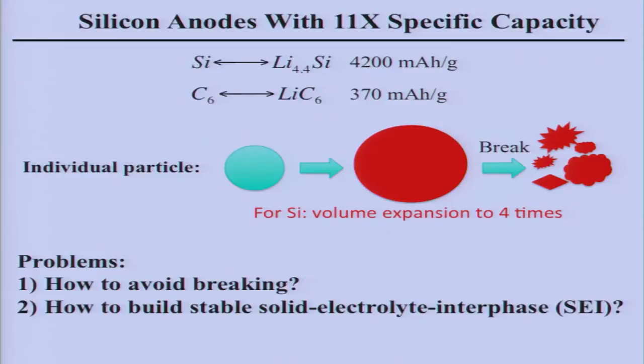So silicon has been my home run since the beginning. This is an example of a silicon crystal structure that can store 1 silicon atom for 4.4 lithium. You calculate that, and this is the capacity you gain. It's 11 times that of graphite carbon. But the problem you're facing is that silicon volume expands to 4 times. Once it expands 4 times, it breaks. You lose electrical contact, and many other bad things happen.